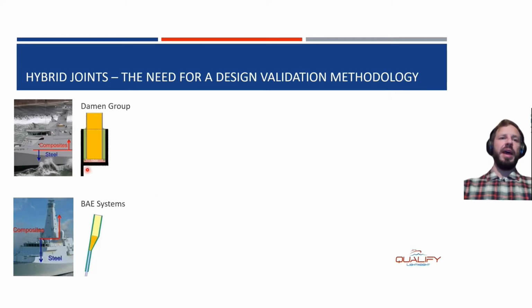In the Damen Group joint, we have a U-shaped steel part with a thick adhesive that is glued to a composite panel, which you don't see here on the other side. Separated between them, you have balsa, and on the bottom, you have some foam, also for separation. The BAE Systems joint has a relatively thin adhesive that connects the steel to the composite. Here you have a hardwood wedge and a balsa, again, as a separator.